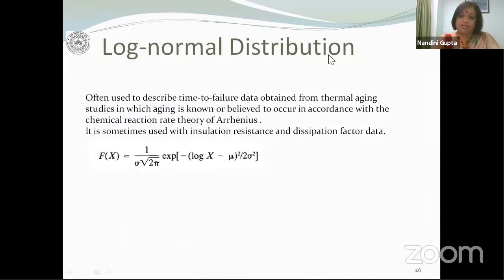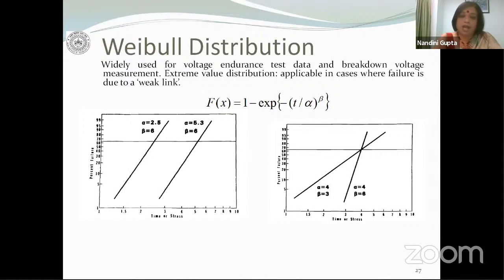Sometimes instead of using normal distribution, we use log normal distribution. For example, for aging data, we do use log normal distribution because not all the time we are looking at breakdown characteristics. In fact, whenever we are looking at any aging property governed by the Arrhenius reaction rate, we can study the data by fitting it to a log normal distribution. The log normal distribution is nothing but a normal distribution where, instead of the value of the random variable, we take the logarithm of the value of the random variable. But in case of breakdown strength, we actually look at Weibull distribution. This is widely used for voltage endurance test data and for breakdown voltage measurement. This is an extreme value distribution.